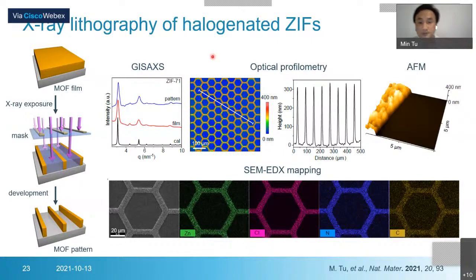So here we just show some characterizations. Here we have grazing incidence SAXS measurement. We can see that after the patterning, the structure doesn't change. And from the optical profilometry, we can see the high quality of the MOF patterning. You see the periodical structure, and also from the AFM and SEM measurements, we can see the exposed area being completely removed. So it's a kind of clean patterning.